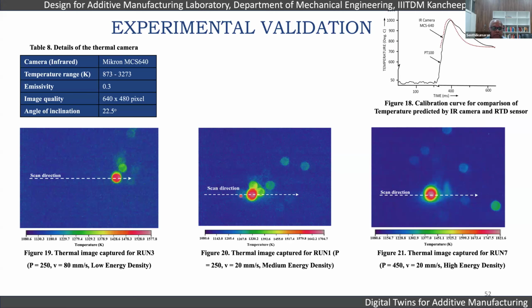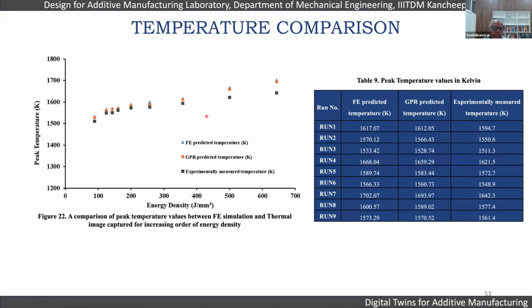We also did a temperature validation. Whatever temperature we obtained, we did validation studies with the thermal camera. So we measured the actual temperature profiles using the thermal camera, and then our simulation is getting validated. We did the calibration of the camera for its accuracy over a wider temperature range. You can see that the FE predicted, the GPR predicted and the experimentally measured temperatures are in close correlation.